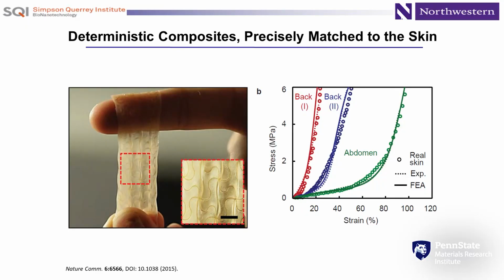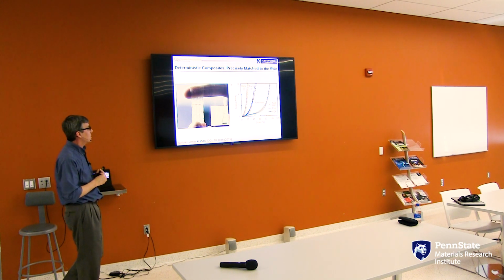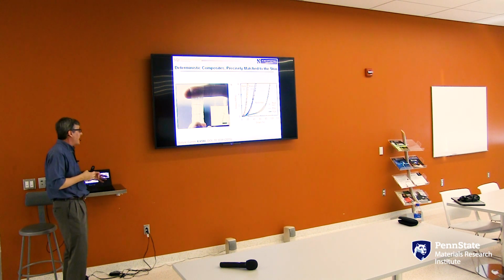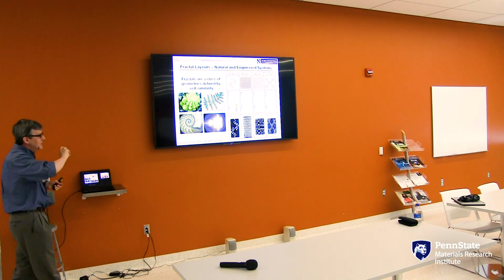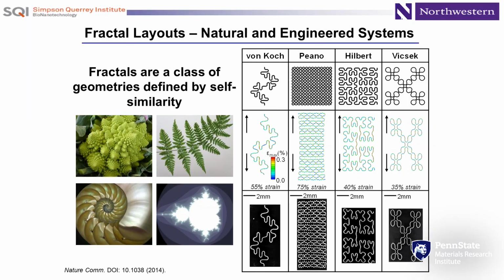So for example, here we've dialed in the geometries and the material properties of these mesh structures to quantitatively match the full nonlinear response of skin from different regions of the human body, two different regions on the back, one on the abdomen, where we have inverse design algorithms developed in close collaboration with Yonggang Huang's group at Northwestern that allow us to define layouts to hit the kind of mechanical properties that we want. So you can quantitatively do this matching, and this becomes fairly agnostic to the materials properties of the mesh itself. You can do this over a very wide range of material classes that are well established for use in electronics and optoelectronics. So those are some pretty simple serpentines, just these interconnected horseshoe shapes.